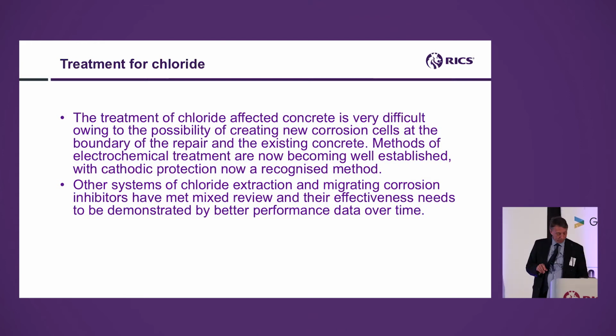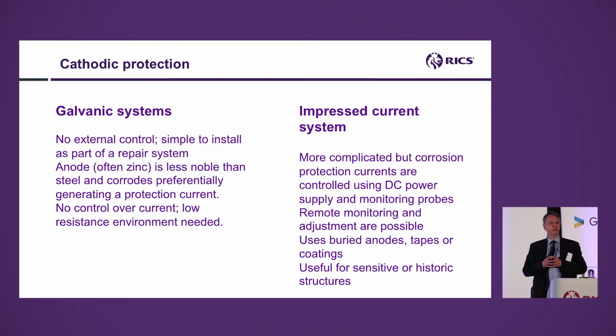Might be. So we've got two broad systems. If you're into car parks and you're repairing those, you probably will come across the galvanic type, which is just like a little zinc pellet wrapped in mortar with some wires sticking out of it. You open up the concrete, put this contraption in, attach it to the steel rebars, and it merrily, in a somewhat uncontrolled way, corrodes sacrificially and prevents the steel from corroding further. So relatively cheap and cheerful. You haven't got much control over it. It doesn't last forever, and you can't really monitor what's going on. But it's a valid repair system where you've got high chloride.